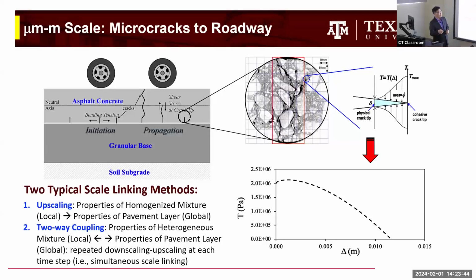Or we can do an up and down looping process through homogenization at each time step, so that we can directly address microstructural change, evolution, in the pavement problem, which is true in this particular case because we're going to get cracks evolved. And then we're going to get some aggregate orientation, maybe some changing over time too. So that microstructural change should be addressed. And also, two-way coupled multiscaling is beneficial in order to consider both mixture design and structural design together, because we consider small scale microstructure as part of the entire process.